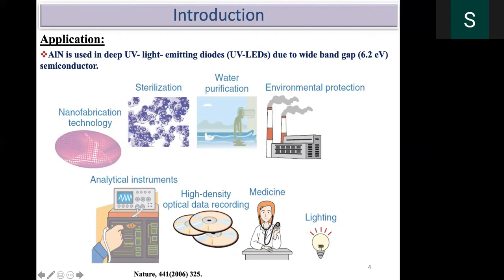And particularly the lighting, gallium nitride is a very good LED material, which can be alloyed with either aluminum or indium. These alloys make very good LEDs, but you cannot grow it on a silicon substrate, which I will show you in a few slides. It is very difficult to grow LED material, that is gallium nitride, over any silicon substrate, because the lattice mismatch problem is there. But when you grow it on aluminum nitride, particularly the A-axis orientation, the growth is possible because they match the lattices. That is very important information.